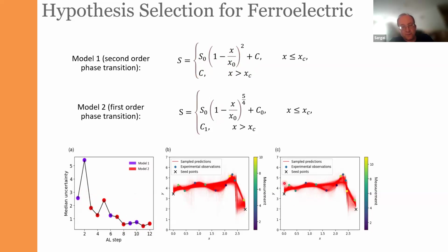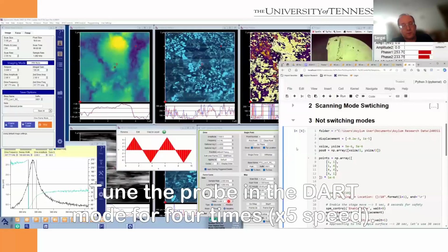actually fairly close. Secondly, the reason why it didn't work particularly well is because realistically, the properties of the material show the peak around the morphotropic boundary, but neither of the models predict the peak. So both of them show the monotonic decay of the data. So this is the example when neither of the models is correct. So it worked somehow, but not super good.